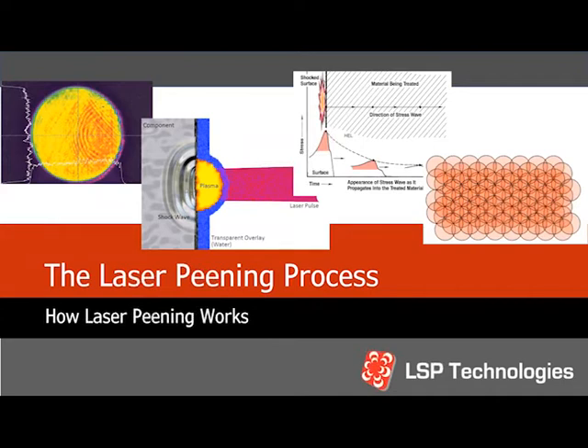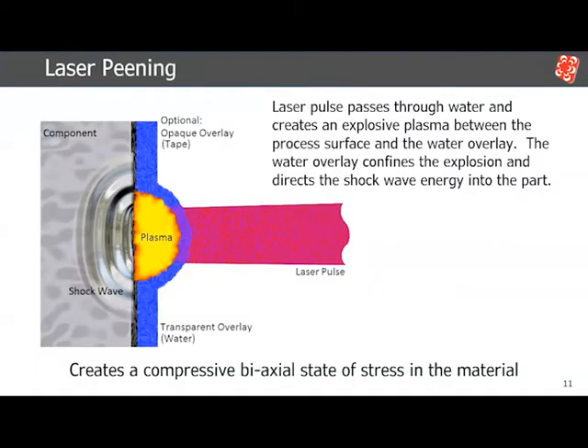So now moving to the part where I will give a brief introduction to laser peening for the general audience. So in laser peening, as you know, we're using a pulsed laser that interacts with the surface of the material, and that generates a plasma. We use a transparent overlay in order to confine that plasma. That overlay is considered transparent since the laser passes through it without losing too much energy. While it confines the plasma, it pushes the energy from the plasma into the material, creating a shock wave. That shock wave is what generates the compressive residual stresses that I will be talking extensively about today.